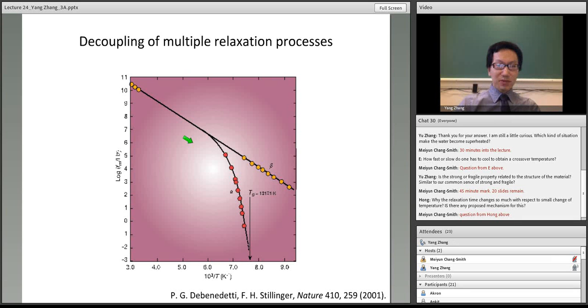So multiple relaxation is one of the phenomena that happens while approaching the glass transition. And actually, there are many more happening. We'll go through them one by one. The next one that I want to talk about is the so-called decoupling of multiple relaxation processes. Here we have two relaxations. In this figure, I plot the relaxation time versus 1/T. The slowest relaxation time is always called alpha, and the second slowest one is called beta relaxation.